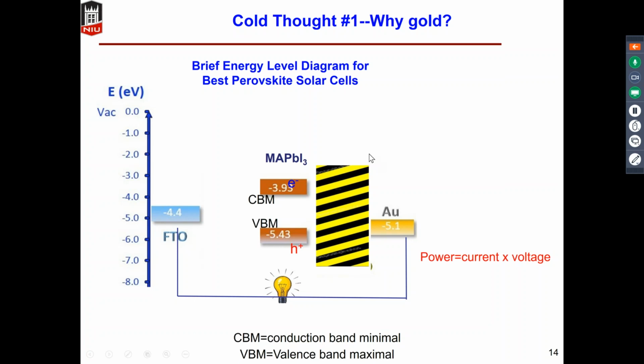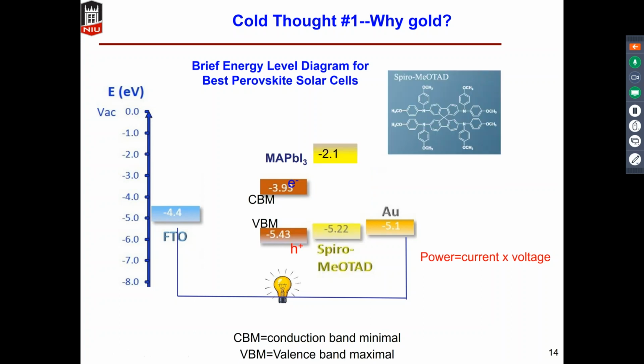And the material suitable for this layer is this spiro-MeOTAD. This is the organic based electron blocking layer, or the so-called hole transport layer. It has a LUMO way above the conduction band minimum of MAPbI3, but with a HOMO orbital between the VBM and the electrode, which is gold here. I will later explain why we have to use gold.